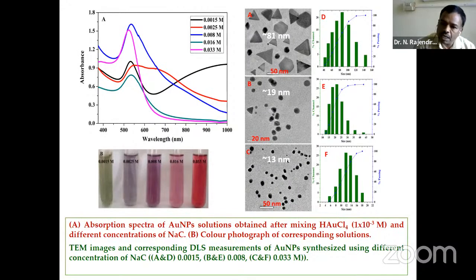Why is it so? Since it behaves as a strong reducing as well as a stabilizing agent, at low concentration the reducing functionality is very low, because it reduces the auric chloride or gold chloride in a slow manner. Because of this slow reduction, the reduced particles have enough time to arrange in a particular shape. So at low concentrations, it favors the formation of anisotropic nanoparticles, whereas at higher concentrations, the reducing functionality is very high, the reduction process is very fast, so the particles are mostly spherical. These things were confirmed by TEM and DLS measurements.